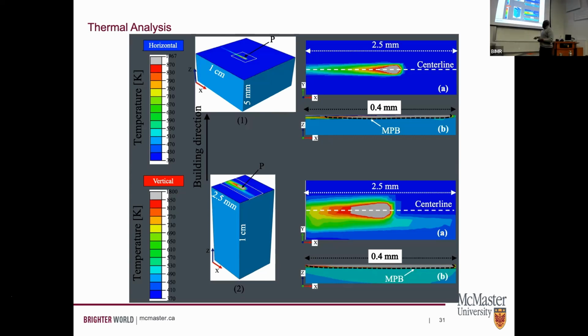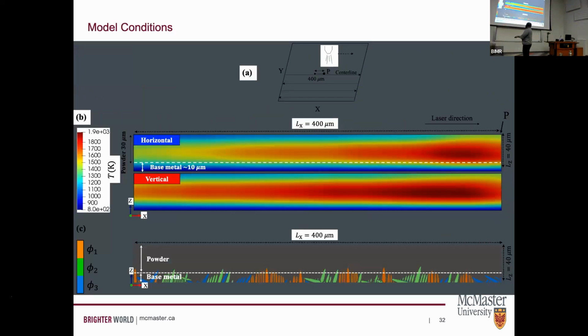It turns out that for the two different directions, you actually see different melt pool geometries as well, which is already suggestive of why they would develop different microstructures. And so what we have here is a substrate or base metal that we assume is some polycrystalline microstructure already. What we're doing is applying this temperature profile, the two different ones, and then we're seeing how this new single layer emerges.